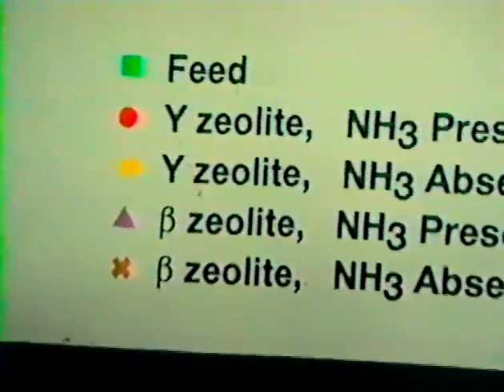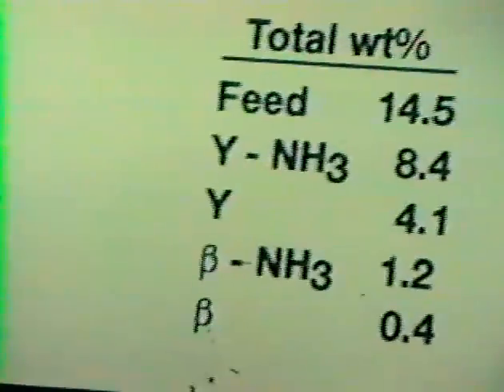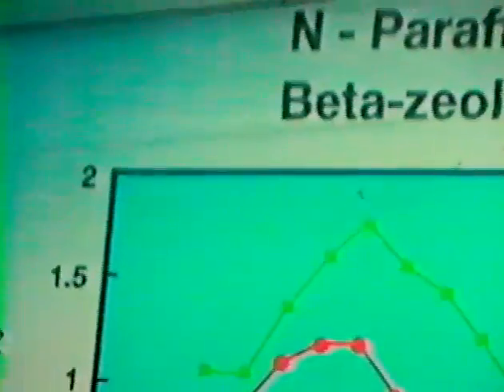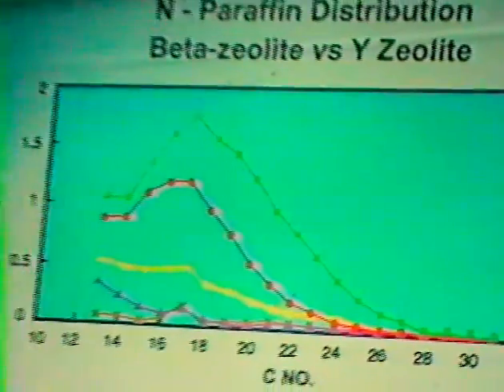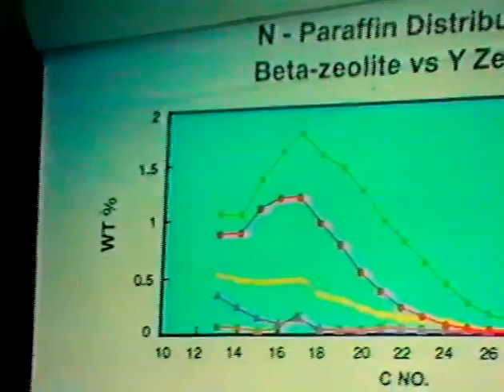Next slide shows what happens to heavier normal paraffins over two different catalysts. The green curve is the feedstock entering the reactor for C12 to C30 hydrocarbons, which are the total weight percent of 14, these are normal paraffins, 14.5 weight percent. If we process it over a Y-zeolite catalyst in the presence of ammonia, we reduce the total of normal paraffins to 8.4, and Y-zeolite in the absence of ammonia reduces it to about 4.1 weight percent.